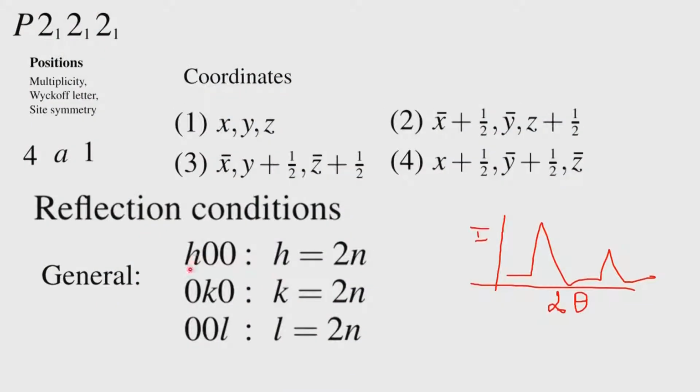You should know what systematic absences you should look for, and in what way you have to do this diagnosis. The diagnosis follows by looking at the general reflections, then the projection reflections, and later the axial reflections. Based on that, you identify the symmetry elements which might come. For example, in this particular case, 2_1 2_1 2_1, you examine the 3 axial reflection systematic absences, and if they do appear like that, then we have a situation where we have uniquely determined the space group.